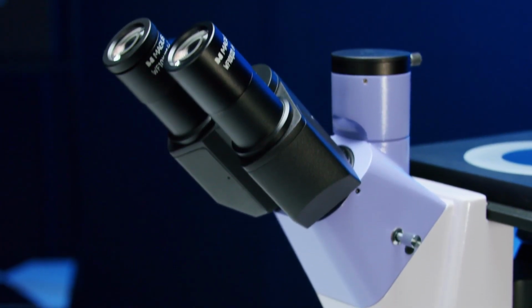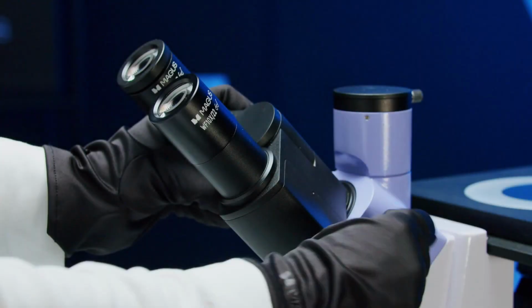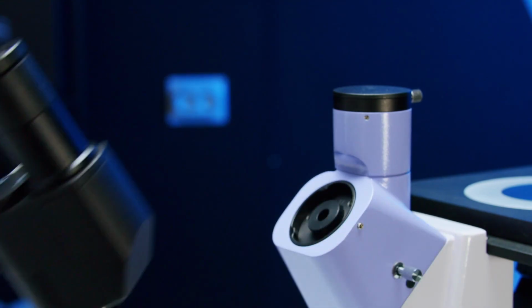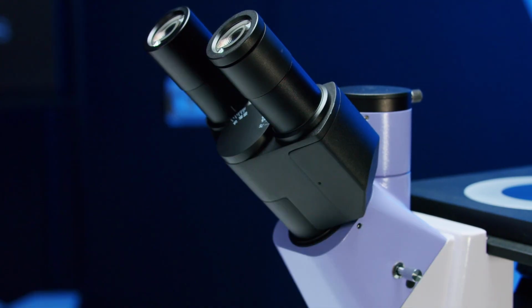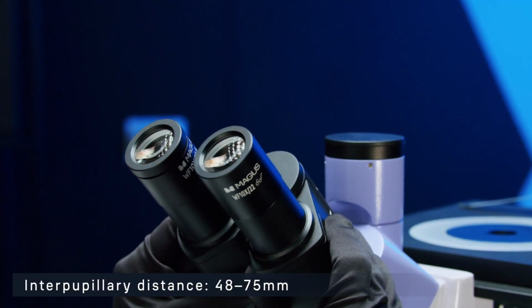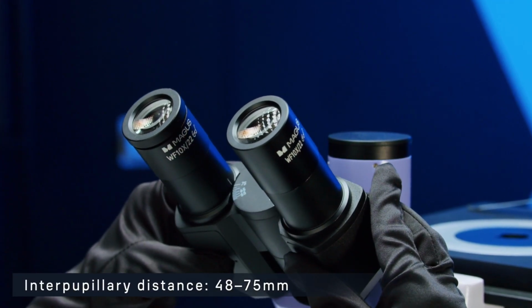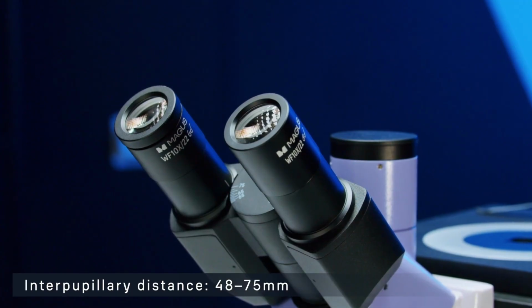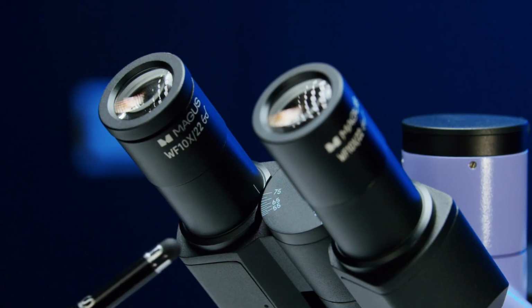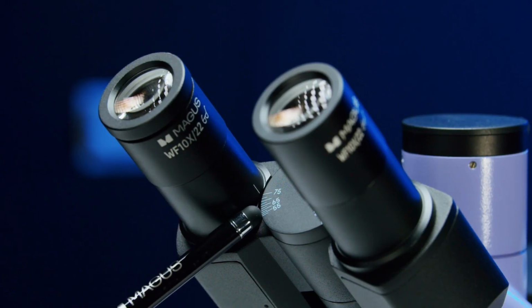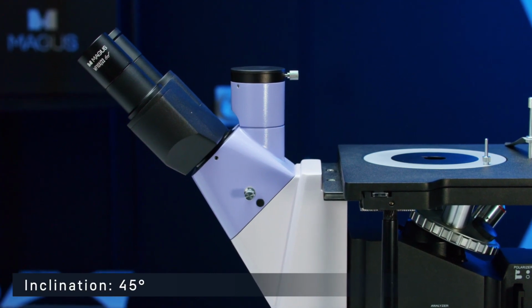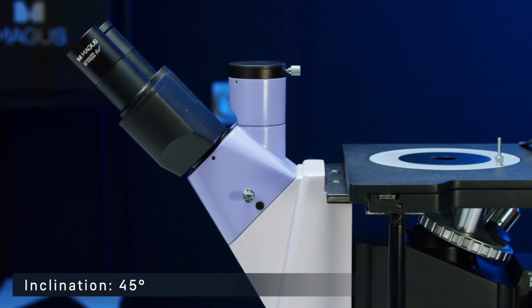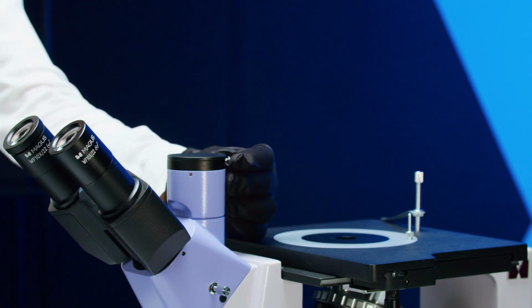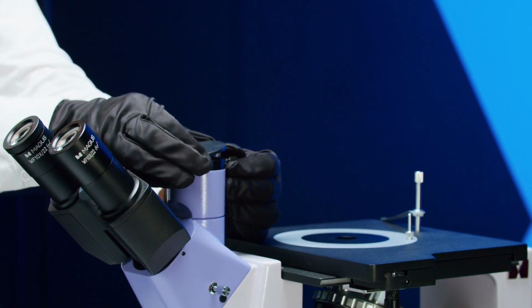The trinocular viewing head is fixed to the stand. By rotating the eyepiece tube block, the user can adjust the eyepiece height to suit their stature. The interpupillary distance can be adjusted within a range of 48 to 75 millimeters. The distance value is read from the scale on the head. The viewing head has a tilt angle of 45 degrees. A visualization system is installed in the vertical tube via a C-mount adapter.